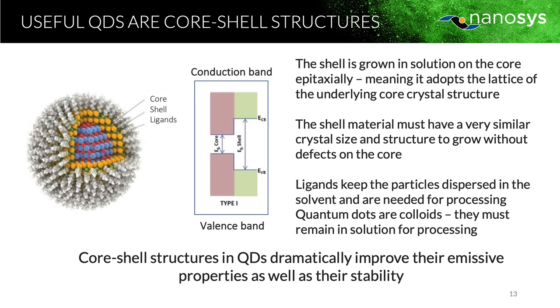So what I told you so far is relatively straightforward. The actual situation, like most of life, I suppose, is more complex than that. First of all, they're not typically just semiconductor particles. They're typically core-shell structures. This was a seminal discovery that happened in the 90s, where they found that by growing a shell around these core semiconductor particles, the optical properties would be drastically improved. If we look at the band structure in the middle here, we see that the core on the left has a smaller band gap than the shell on the right, the green colored band.